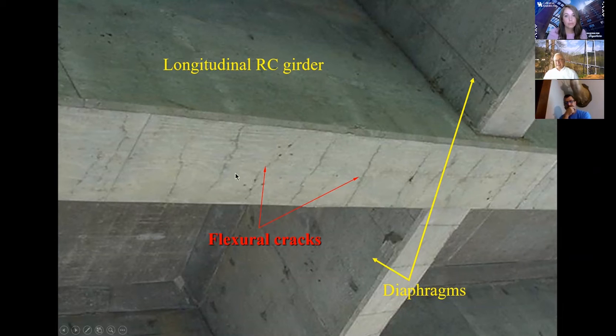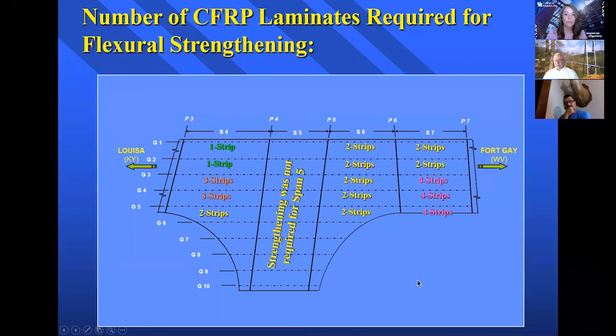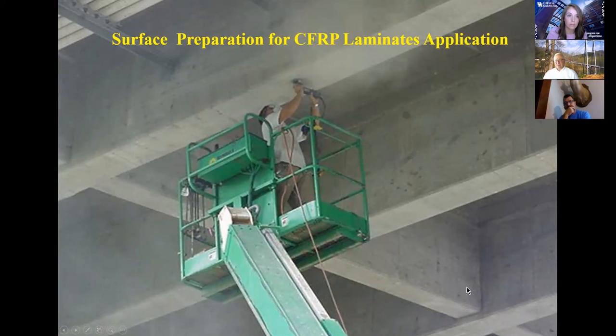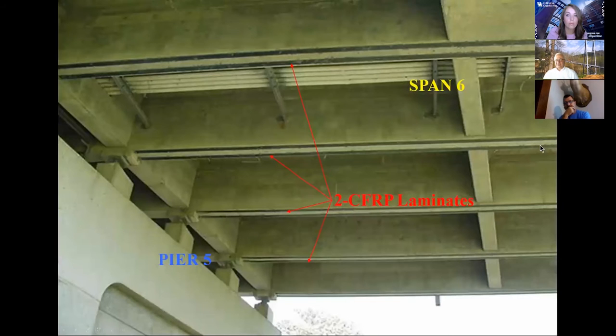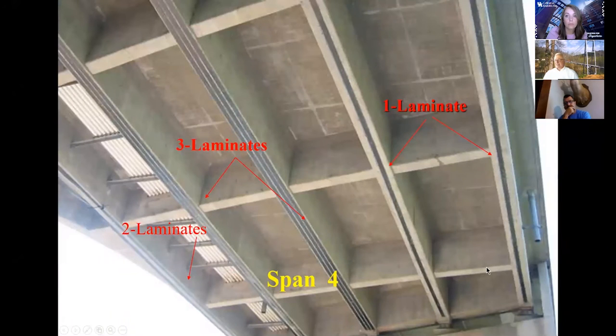But the problem was that every month we used to go to inspect the bridge, we would see more cracks forming on the soffit of the beams. And since this bridge is really very critical for both Louisa and Fort Gay, the state decided to retrofit it. So we used this laminate to do the retrofit. We do, of course, all the analyses first to see how many of these laminates we need to use. We start preparing the surface, apply the laminates, and this is the finished product. We don't use this material anymore. It has many downsides that I won't go into.